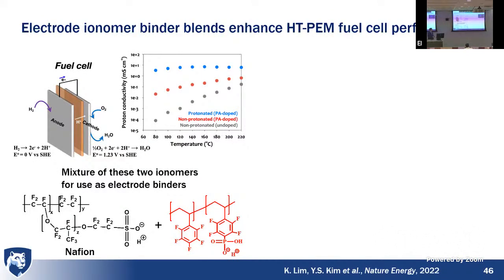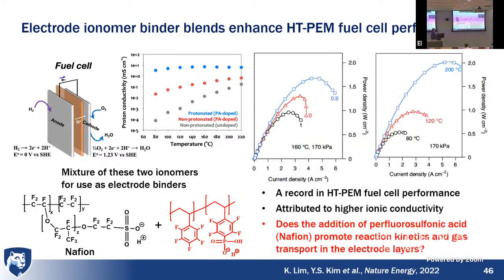There's a new class of binder materials where they take this phosphonic acid ionomer and mix it with your traditional low temperature system, Nafion, this is a fuel cell system. This is from Los Alamos, where they said, okay, we mix these two, right? We get higher conductivity in the electrodes. And when we get higher conductivity in the electrodes, we get higher power density, right? So the black line is we just have Nafion. The red line here is we just have the phosphonic acid ionomer. And if we mix the two, we get higher. And this is at 160 C.